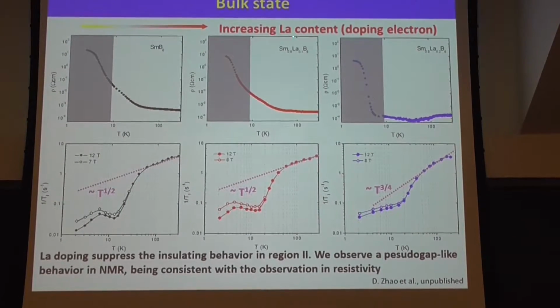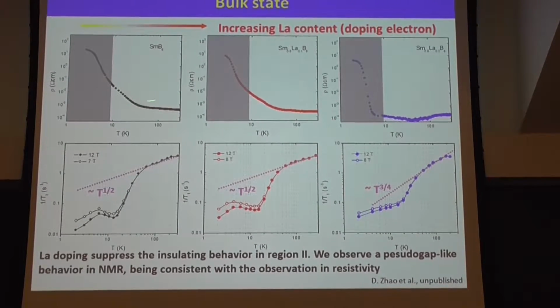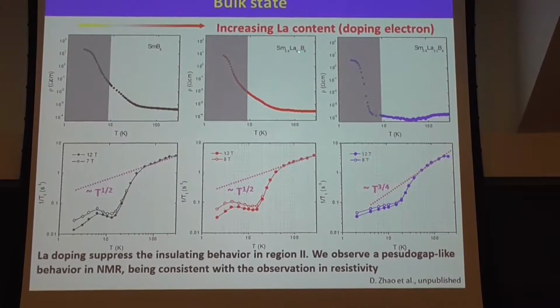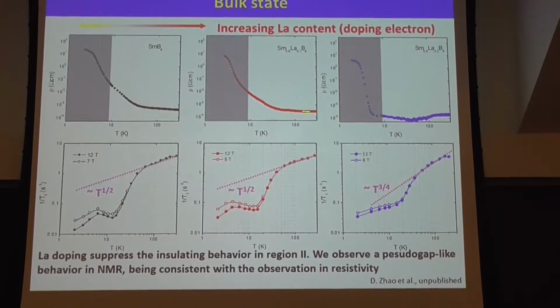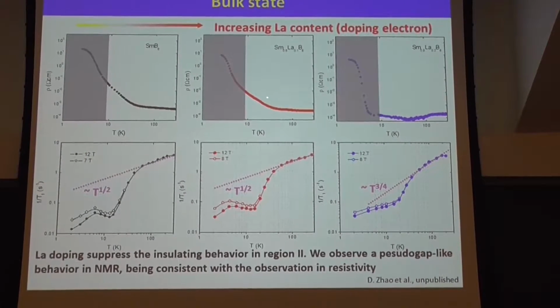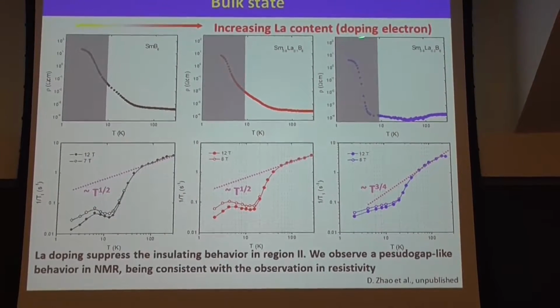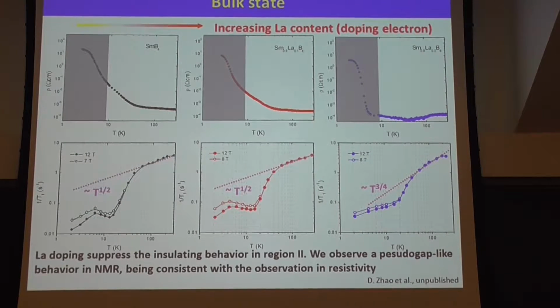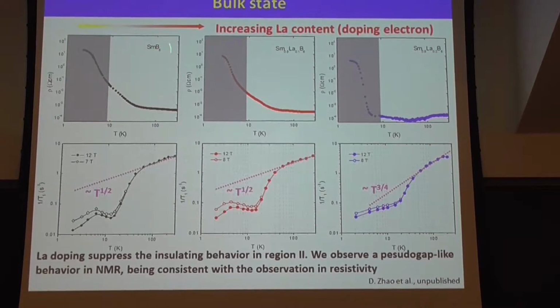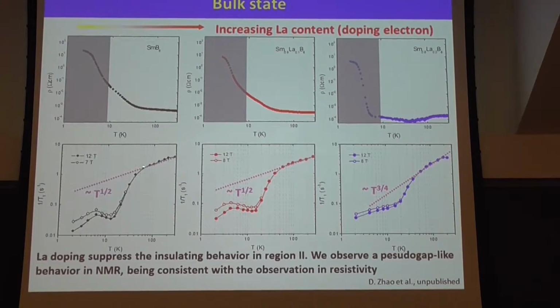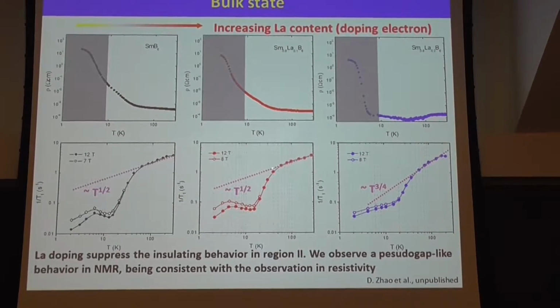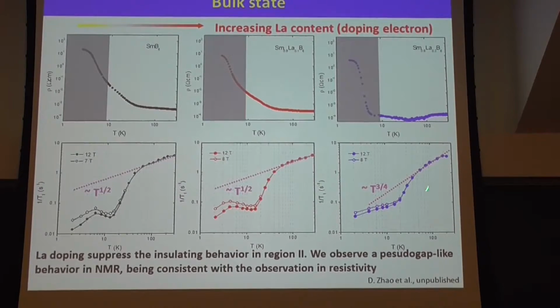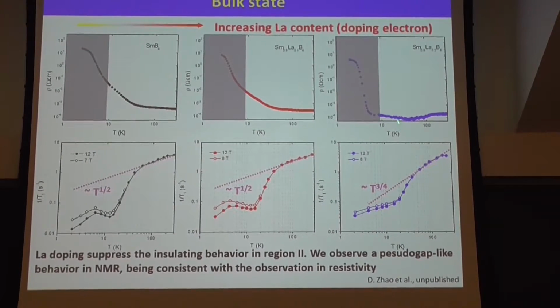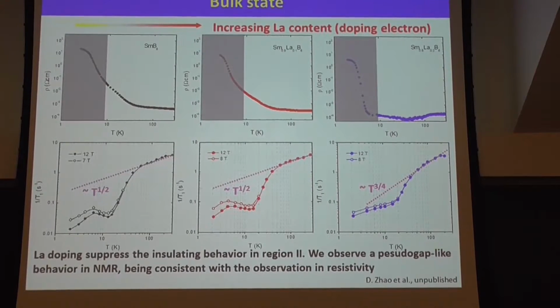Our group also used lanthanum doping on samarium hexaboride. This is samarium hexaboride, using lanthanum at 10% and 20%. You can see in this region, this gap is suppressed by this lanthanum doping. This doping is electron doping. You can see that NMR also shows, for the samarium hexaboride on top of the sample, some hybridization gap is here. But with this one the gap is suppressed, and with this one the gap is also suppressed. This gap is consistent with the resistivity measurement data.